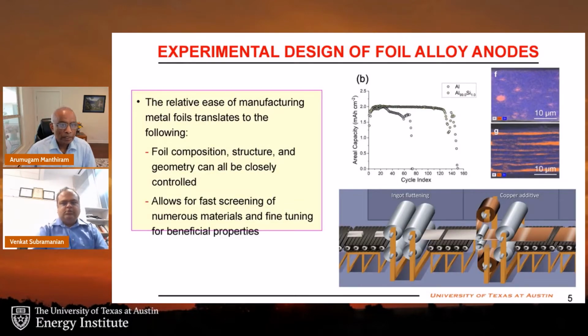So the experimental design is very easy. Making these materials is very easy, and we also have a lot of flexibility for compositional, structural, and geometry tuning with this approach. For example, if you add 1% of silicon to aluminum, you can see a big difference in the performance. It also allows for fast screening of various materials, because you just make the metal foil anode, just a foil, and then test them, rather than going through making slurry, casting, and then electrode drying. All those very tedious steps can be avoided.